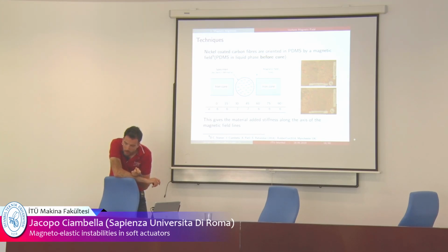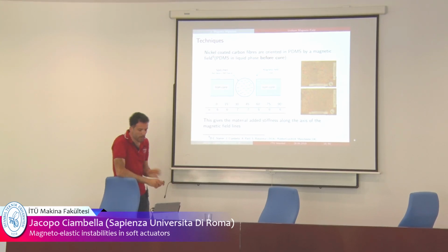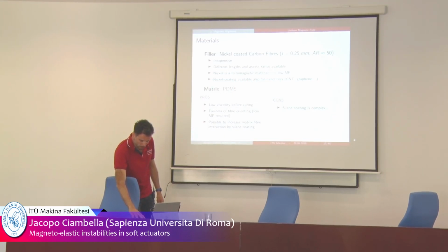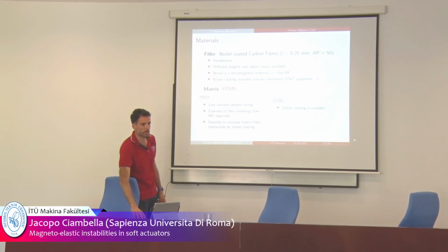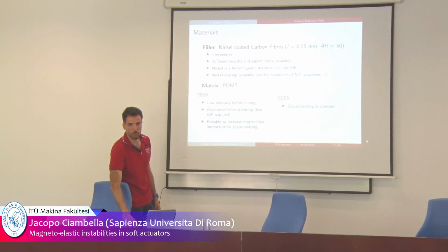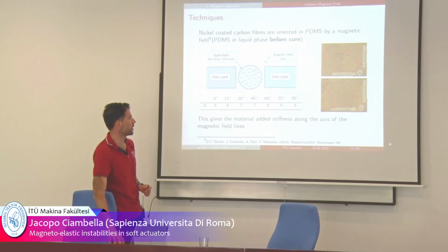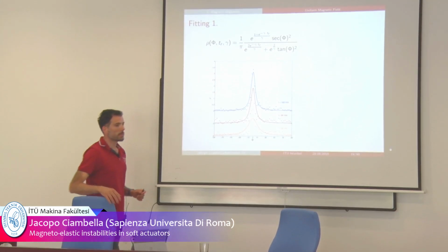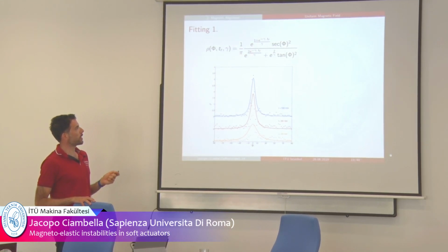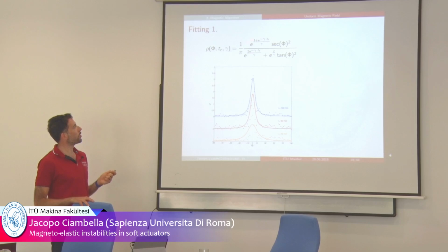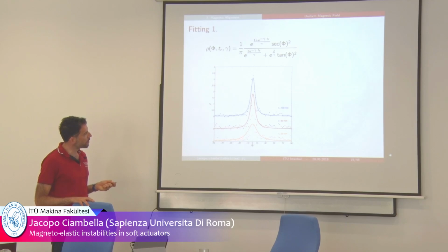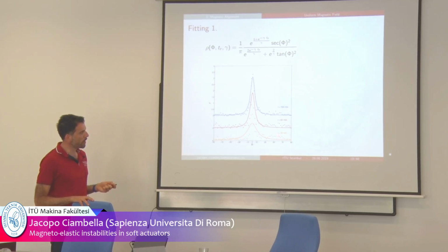We also observed fiber agglomeration, which is detrimental for the mechanical properties. And consider that the percentage in volume, I think it's written here, was only 6% in volume. I didn't mention that, so a relatively low percentage of fiber reinforcement. These are the results in terms of the orientation. This is exactly the equation I showed you before, which gives you the orientation of the fiber at time tr. And this is how the fiber orientation changes with time, after 20 minutes, after 60 minutes, after 150 minutes.